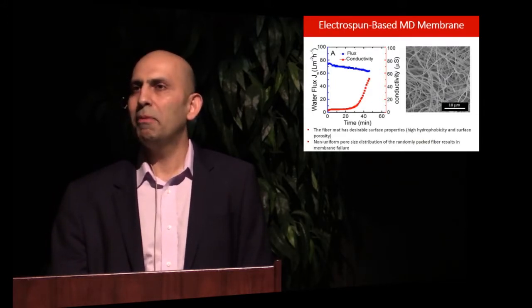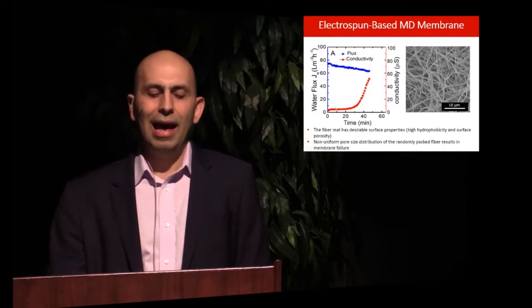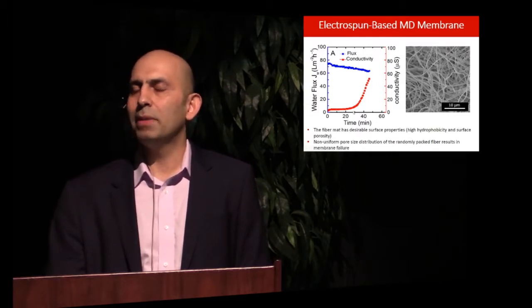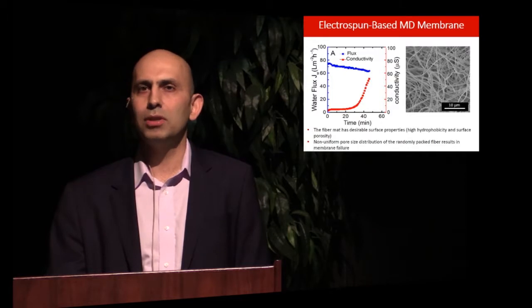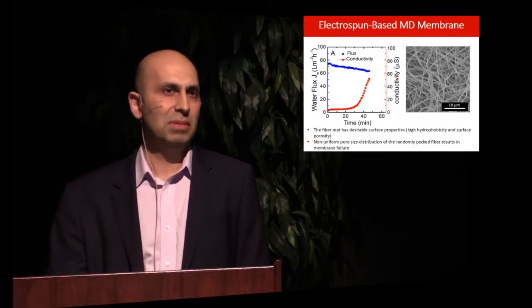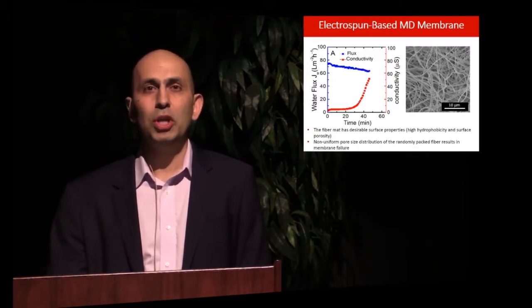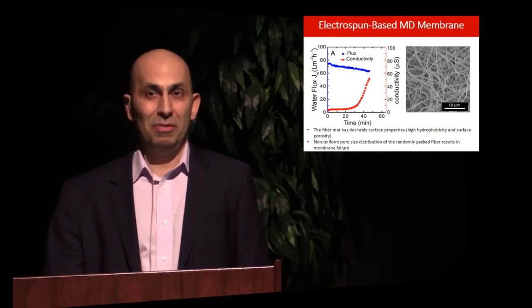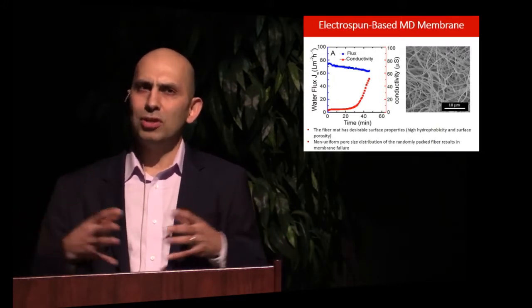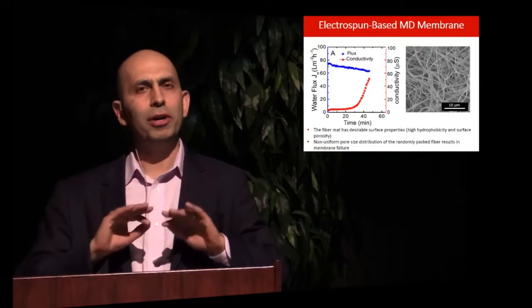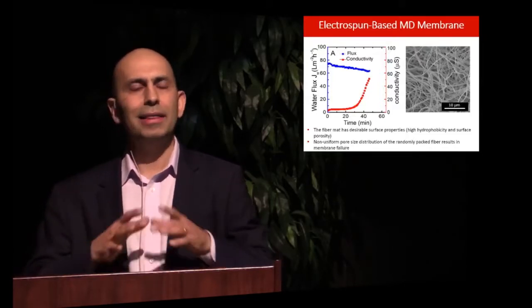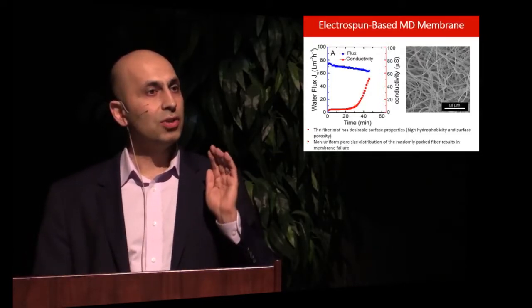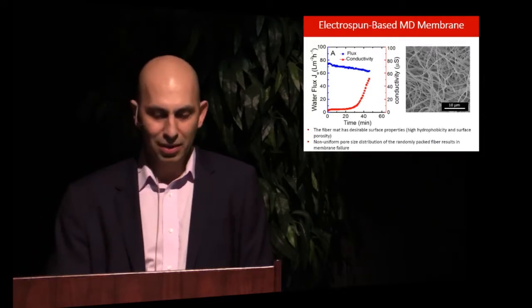But we pay something for that. After 20 or 25 minutes, the salt starts diffusing through this membrane. That means it's a failure. So we need to adjust the pore. We need to make it open enough, but we need to adjust the pore in the meanwhile. Otherwise, the water will break the meniscus at the entrance of the pore, and as a result, the process fails.